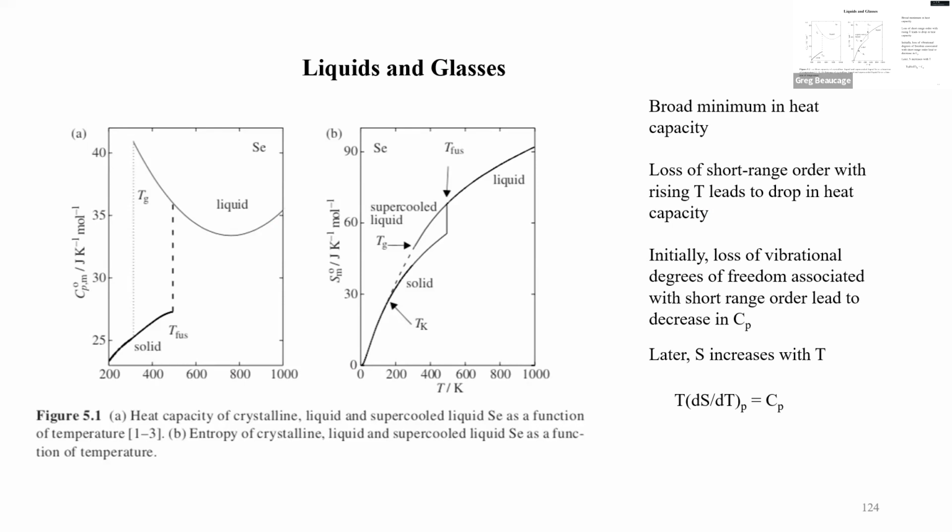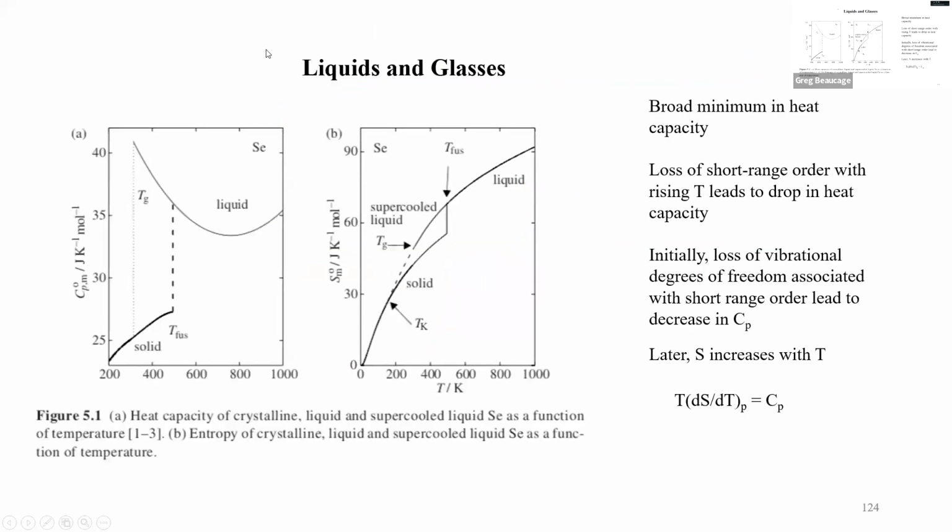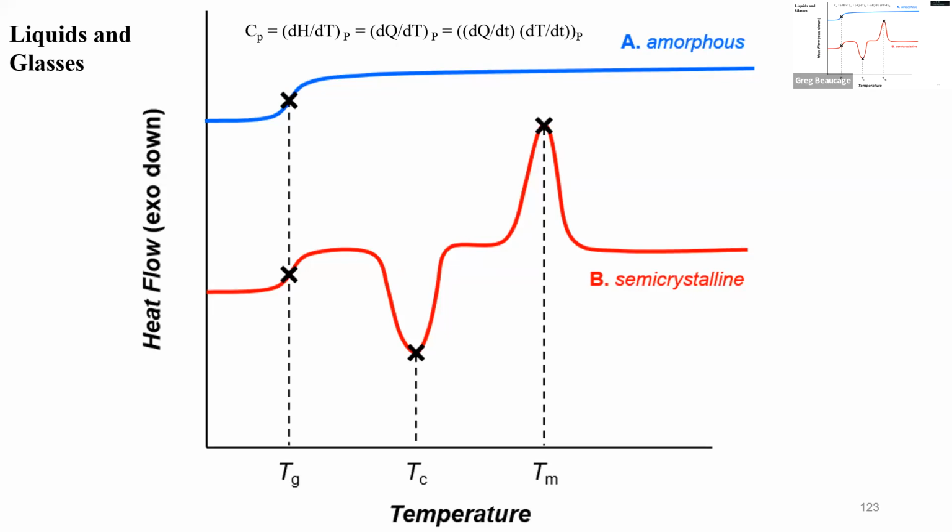Anyway, the glass transition is another thing, right? In the DSC, we saw the glass transition is going to be this kind of knee thing, and you can get an overshoot on it. If you heat fast, going from a glass to liquid, if you zip through it, you'll get a spike here that looks a lot like an enthalpic transition. It's kind of like the material gets stuck and then it releases, and that release can lead to something that looks like an enthalpy. And you can get kind of the same thing on cooling, right? People have spent a lot of time on this, because it's an esoteric subject and no one knows the answer.